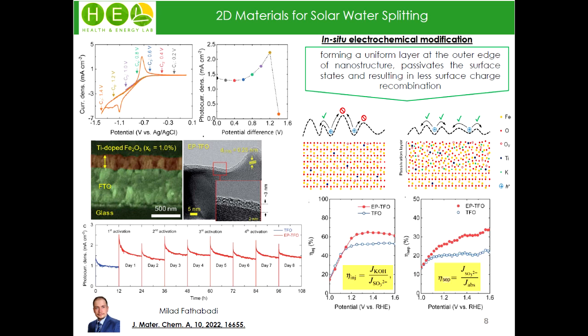So what is the state of the art in terms of photoanode material in real life devices? Are you aware of devices? For hematite, in terms of photocurrent density of such a photoanode, nearly 6 milliamps per square centimeter is a good record. But this is usually not for pristine hematite.